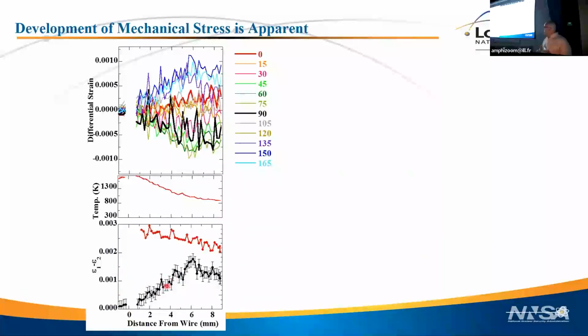So what this black line is, is the difference between the strain in the normal to the surface direction and the transverse to the surface direction. What is distance from wire? That's how far you are from the melt pool. Right? So as I move the X-ray beam away from the hot spot. Now it turns out I can't get a stress, again, for the reasons I just said, and because I don't have any good assumption on what the stress should be out of plane. I can't measure a stress, I can't determine a stress in any given direction.